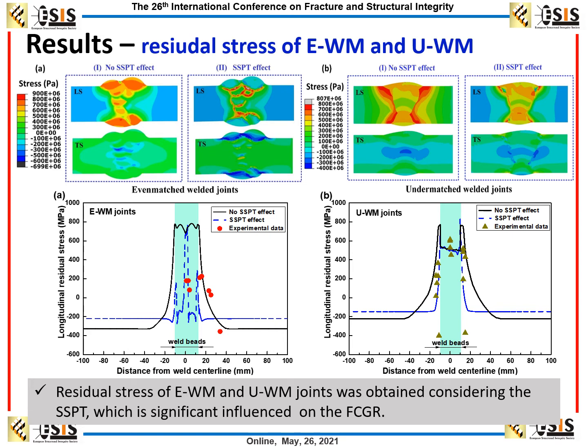As we all know, the residual stress has great influence on the FCGR behavior. Generally, the tension residual stress will accelerate the FCGR, and the compressive residual stress will retard the fatigue crack propagation. Looking at the residual stress distribution of the even matched weldment and undermatched weldment, considering the SSPT effect, the result shows that for the even matched weldment, the simulation result has good agreement with the experimental data considering the SSPT effect.